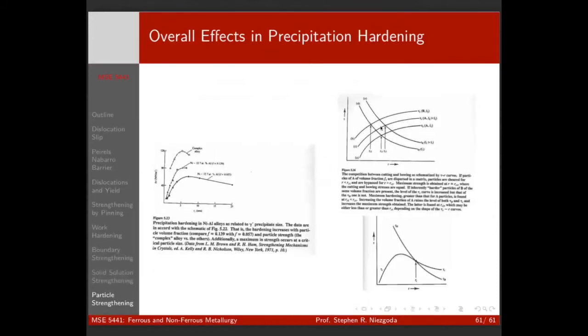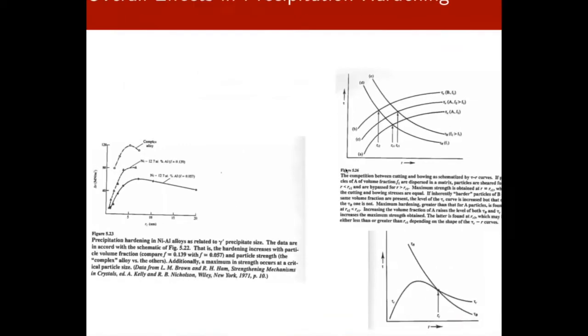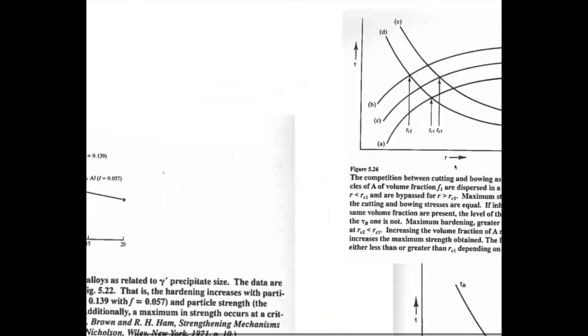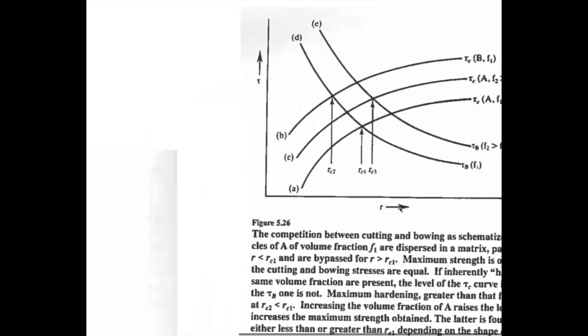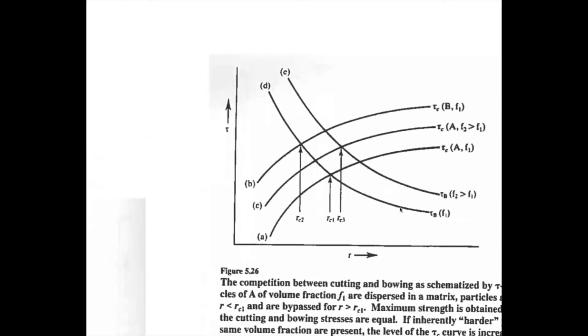Okay? And if we think about this, this is the important picture, right? Generally, there's a competition between bowing and cutting, right? If we keep our volume fraction the same, as we make our particles larger, the separation between them gets larger, right? This is Ostwald ripening, which we'll talk about in aluminum as well. As we make our particles bigger and our volume fraction remains constant, our separation between them gets larger.